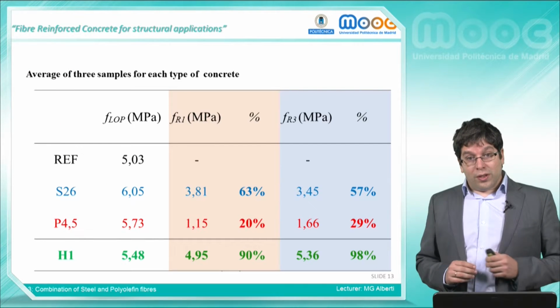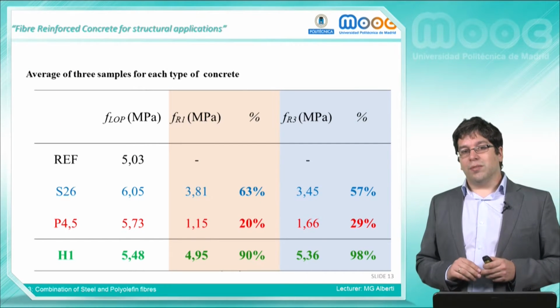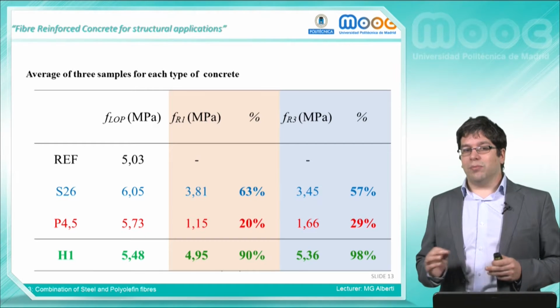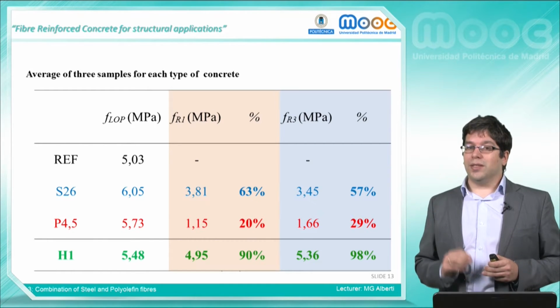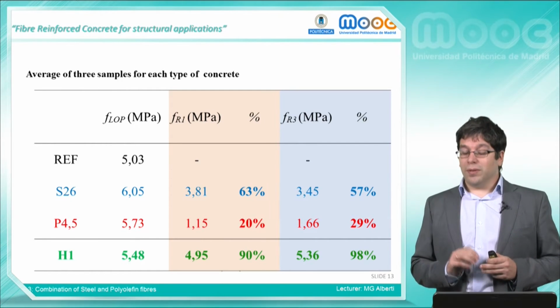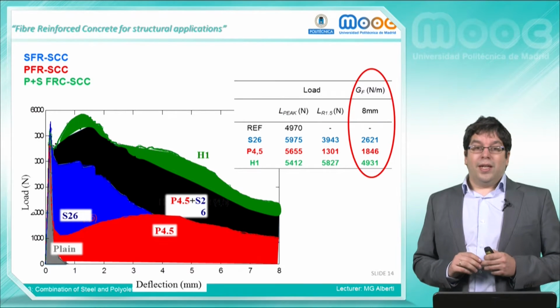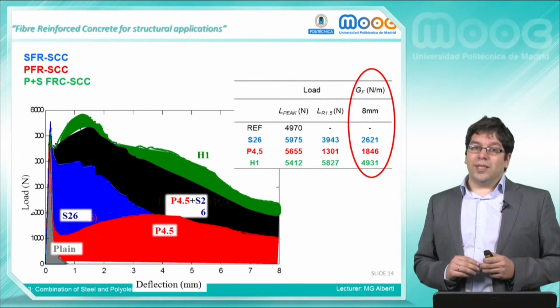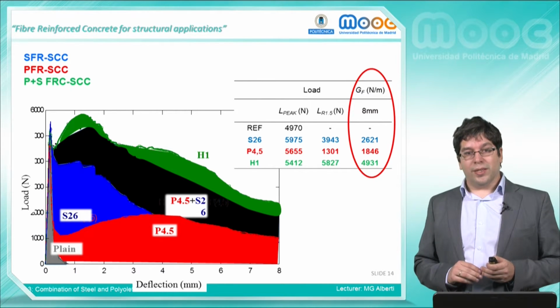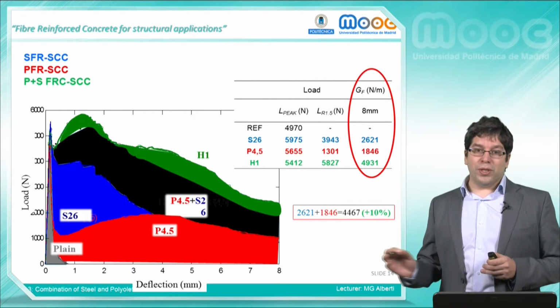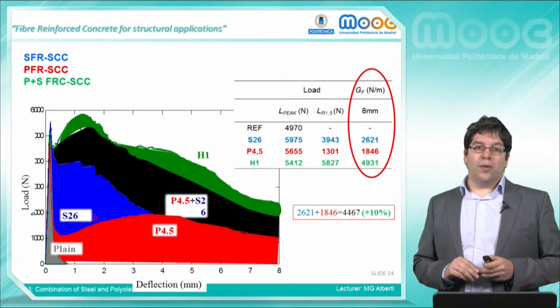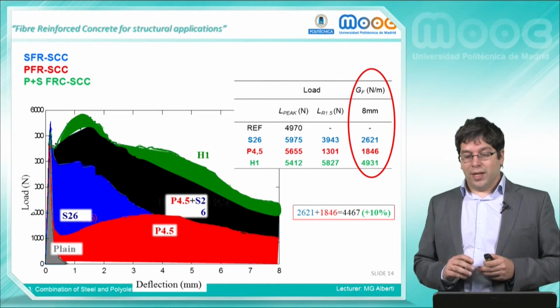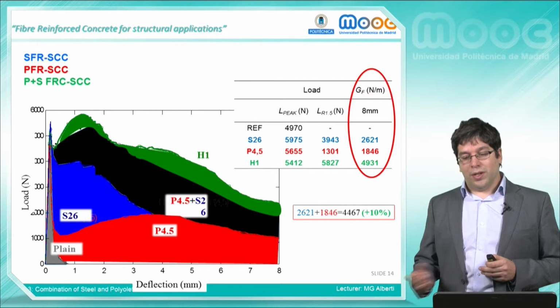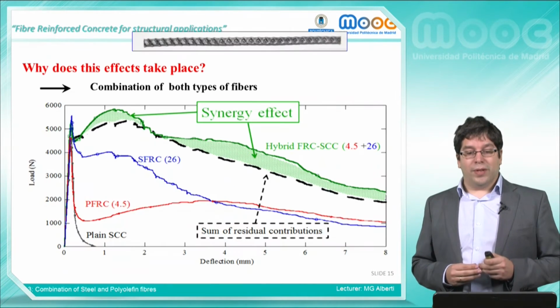And moving on to the residual strengths, it is important to say that it remained above 90% of the strength at the limit of proportionality up to significant deformations. And in terms of fracture energy, it could be concluded that some synergy effect took place, increasing the fracture energy about 10% of the algebraic sum of the individual residual strengths. This green area was therefore a synergy effect.